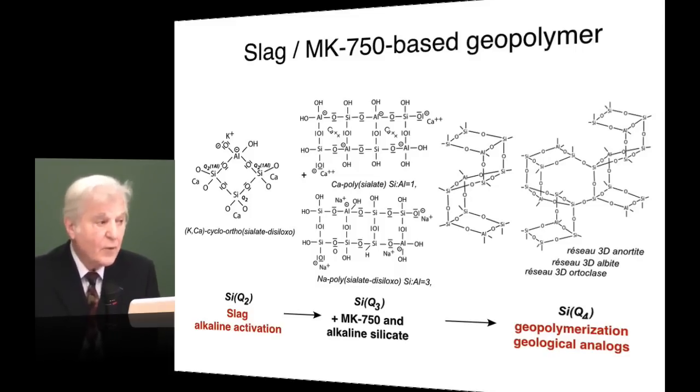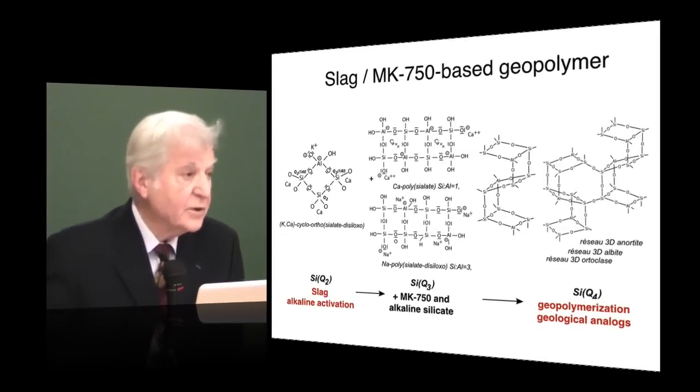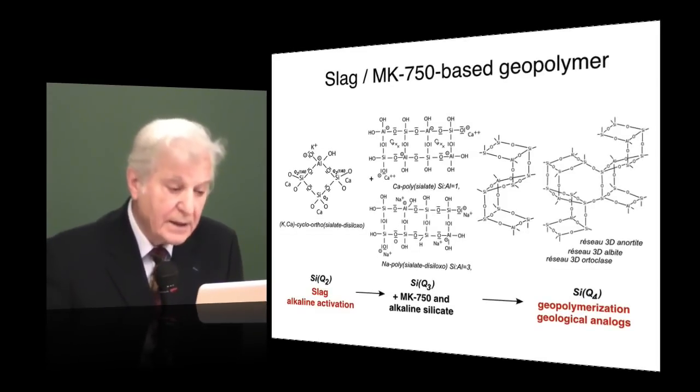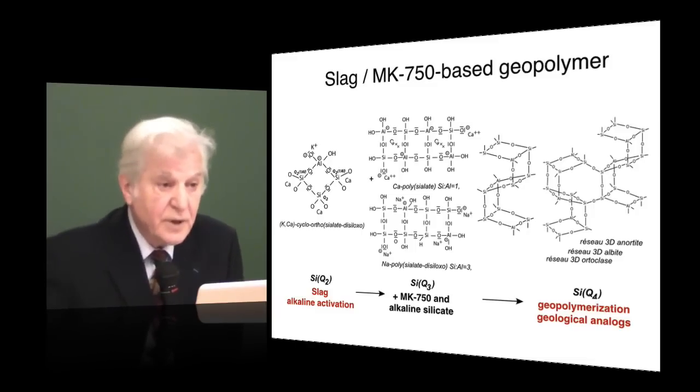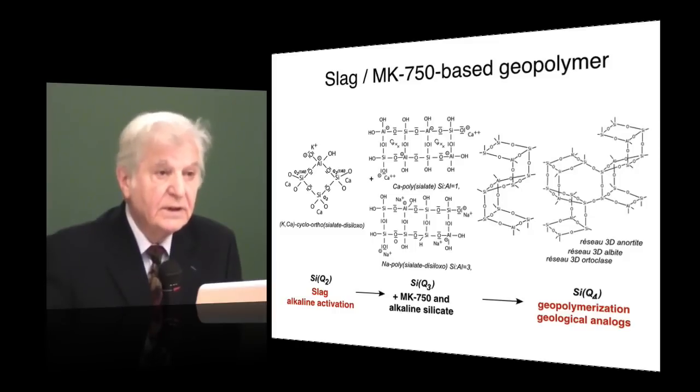this guy provides higher strength. So all the people are just looking at the strength. You get 90 MPa when you just alkali activate slags. I say, wow, wonderful. Here, with a genuine metakaolin-based geopolymer, you only get 60. Bad. Well, in fact, we can also achieve 150 afterwards. But at the beginning, and this is why they claim that alkali activation is better. In terms of strength, yes. In terms of long durability, no.